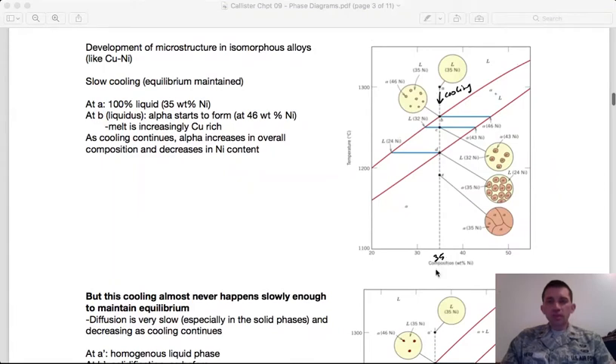So if we have, again, 35 weight percent as our alloy composition, and if we heat it up, say, to 1300 C, we'll be in a fully liquid state. That's what our phase diagram is telling us. If we cool down from there, we'll have liquid until we hit this liquidus line here, and that's where we start to solidify, and the phase that we're solidifying into is alpha phase.